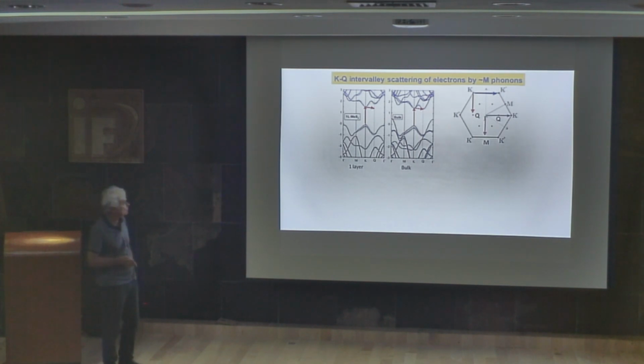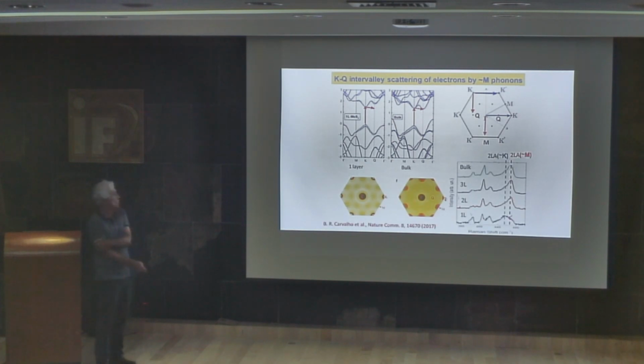Then what we could show is that in the case of 1 layer, we can only see the scattering from K to K prime, this one. And you see the phonon that brings the electron from K to K prime. The vector of the phonon is near the K point. But in the case of bulk, we can have the scattering from K to Q. And the phonon that brings the electron from K to Q is close to the M point.